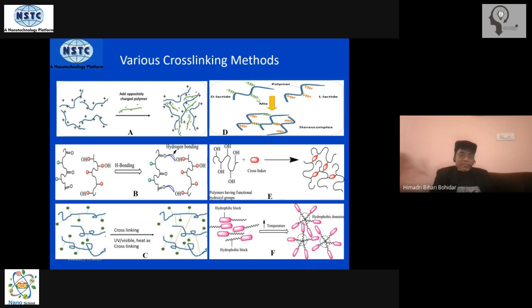Okay, and another example is you can use a cross-linker. Different chains can be cross-linked with the cross-linker. I'll give you an example: if you have pectin, then add calcium chloride to it, and it will turn into a pectin gel with calcium ion being the cross-linking agent.